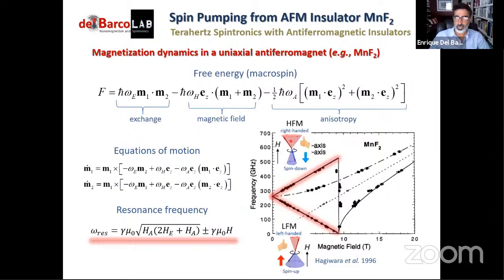The right-handed mode goes up in energy, while the left-handed mode goes down in energy. The difference between these oscillatory modes is that the sublattice magnetizations will describe different precession cone angles. So the one that goes up in energy, basically the resulting magnetization goes down and opposes the magnetic field, and the one that goes down in frequency, the resulting magnetization, because one cone is smaller, so the projection into the C axis is larger, goes with the magnetic field, right?